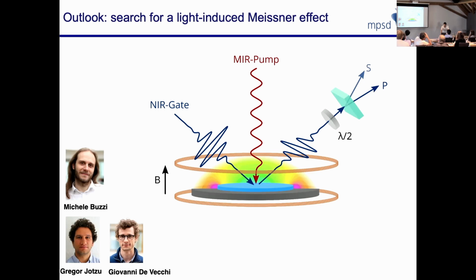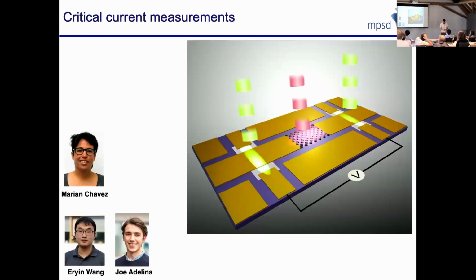And the second thing we're doing now, with quite conclusive information, is that we've learned how to grow C60 in these waveguide devices, where we use photoconductive switches. These are the so-called Auston switches that allow you to measure transport with femtosecond time resolution. We have now probed critical current behavior in the light-induced state. You could compare this to the equilibrium metal where there is no critical current. And you can see critical currents that are somewhat larger than the ones you get in equilibrium. And there's a whole discussion to be had there.